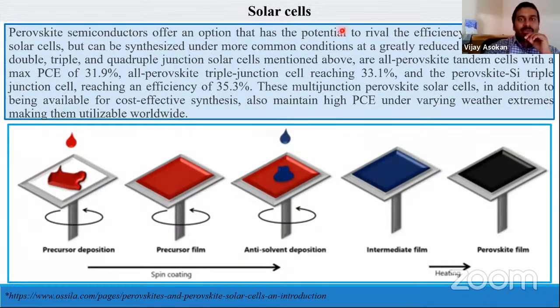The perovskite semiconductors offer an option that has the potential to rival the efficiency of multi-junction solar cells, but can be synthesized under more common conditions at greatly reduced cost, revealing that the double, triple, and quadruple junction solar cells mentioned above are all perovskite tandem cells with a maximum power conversion efficiency around 31.9 percent, all perovskite triple junction reaching about 33.1, and perovskite silicon triple junction cell reaching an efficiency of 35.3 percent. So these multi-junction perovskite solar cells, in addition to being available for cost-effective synthesis, also maintain high PCE under varying weather extremes, making them utilizable worldwide.